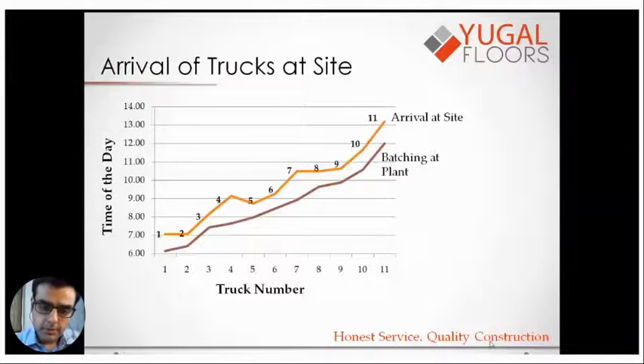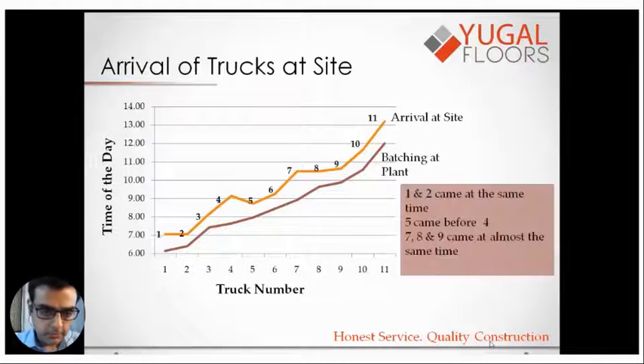All right. So the red line is what you already saw. That is the batching. And now look at the orange line. Orange line actually tells us the arrival of trucks at site. I will deconstruct this for you. Now look at truck number 1 and 2. They came to the site at the same time, even though they were batched at different times. Second, look at truck numbers 4 and 5. Truck number 4 was batched before truck number 5, but it came to the site after truck number 5. Look at truck number 7, 8, and 9. They all came to the site at almost the same time.